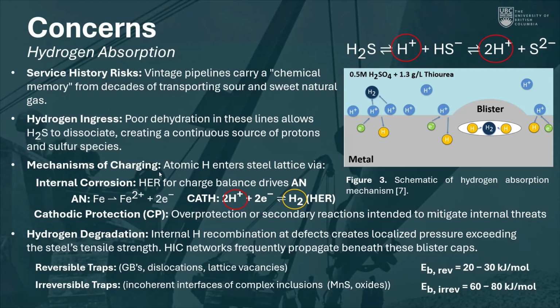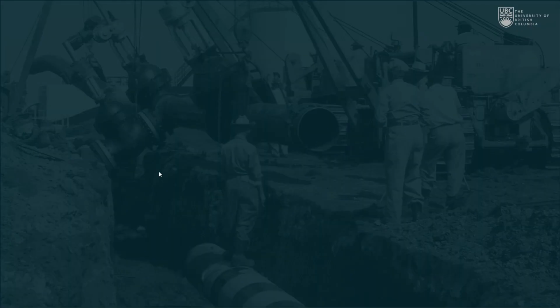They basically act as a sink for hydrogen accumulation within incoherent interfaces. And we typically see these around manganese sulfide inclusions as well as complex oxides. So again, as I alluded previously, manganese sulfide inclusions can be a deep trap site for hydrogen accumulation.